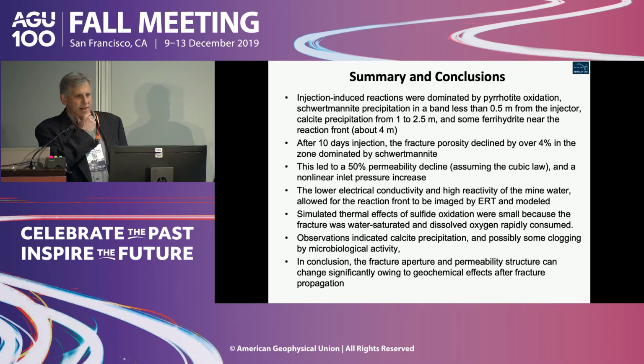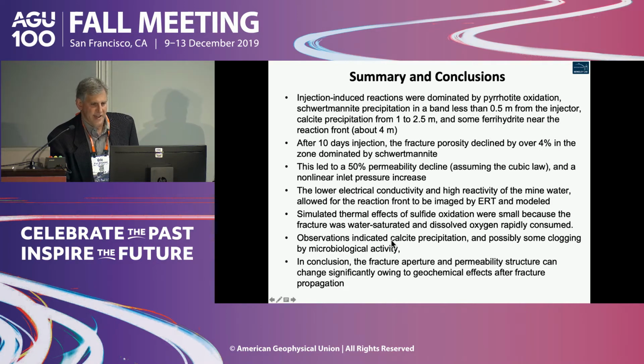So in summary, the injection-induced reactions were pretty obvious. Injecting oxygenated mine water would be dominated by pyrrhotite oxidation, and then a bunch of iron hydroxides, maybe schwertmanite, would be precipitated very close to that region, would suck up the oxygen, and then start precipitating out and dropping the permeability. Calcite does start to form out further, which you observe. And it's a pretty strong effect after just 10 days at a very small injection rate of only about 0.01 kilograms per second.